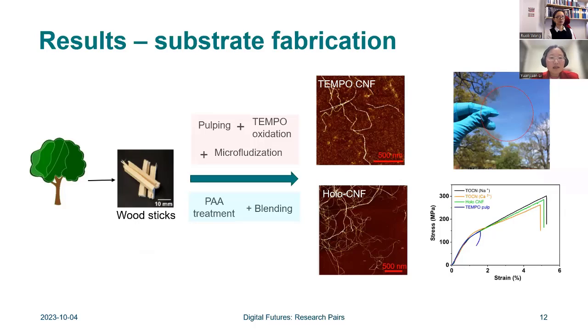Here are the results obtained. We prepared two types of nanocellulose from wood. One type of nanocellulose is TEMPO-oxidized CNF, which has a higher surface charge with better water holding property, beneficial for long-time ultrasound transparency. From the atomic force microscope image, you can see the diameters of CNF are less than 5 nanometers. The other type of nanocellulose is Holo-CNF, which has better printability, beneficial for stable electrical signal collection. Similar morphology was obtained compared with the TEMPO CNF, but with less uniform nanocellulose diameter.